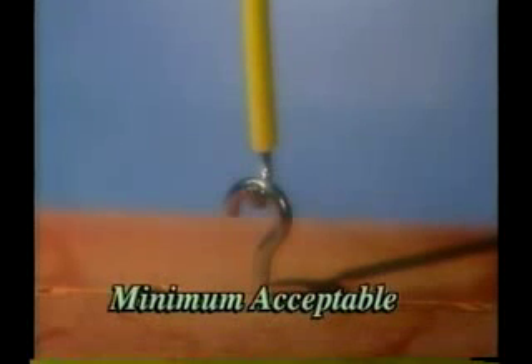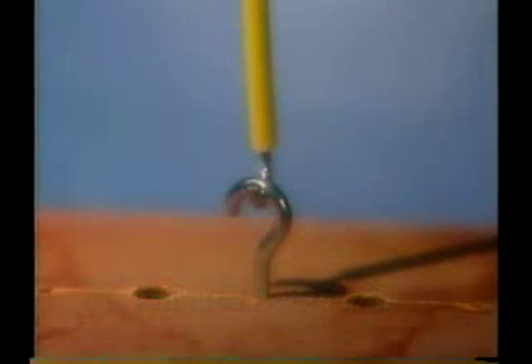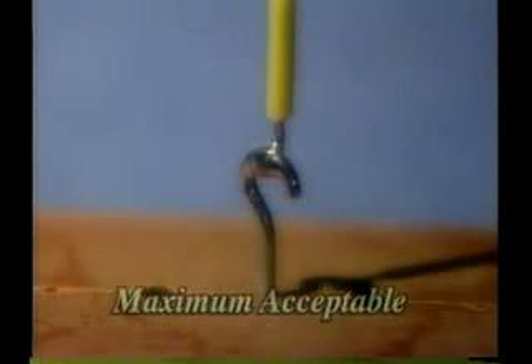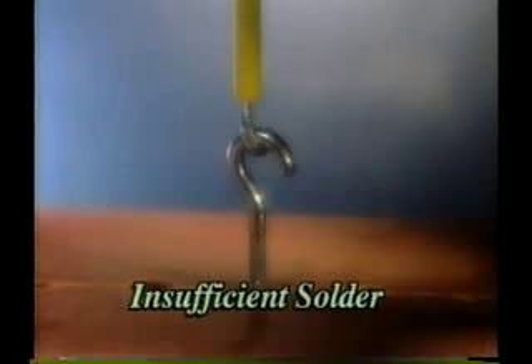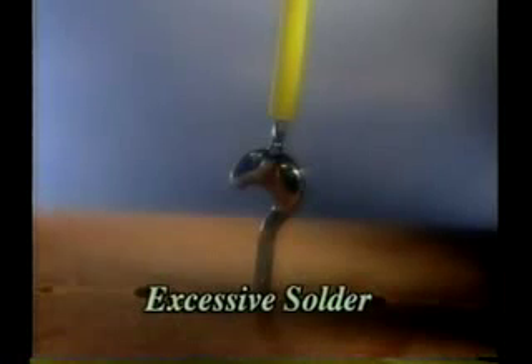The acceptable solder joint will have the same characteristics we've seen so far, that is, slightly concave fillets and evidence of good wetting. Here are examples of the minimum and maximum acceptable solder joints for hook terminals. And these two illustrations reveal unacceptable solder joints, insufficient solder, and excessive solder.